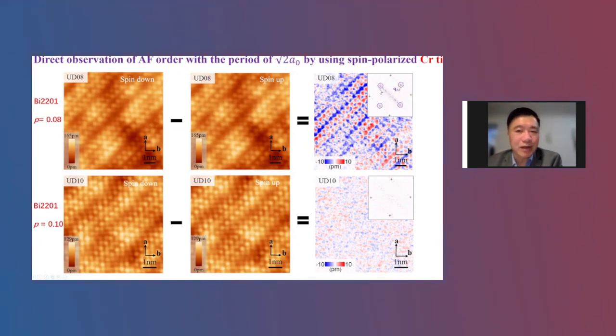So I must say that this is the very first time to directly visualize the anti-ferromagnetic order in the cuprate. Okay, and for the 10% doping, then you don't. We also measure spin down, spin up. Then we subtract. We don't see such order. After Fourier transform, we also don't see the spots. So that means that the anti-ferromagnetic order exists at the 8% doping sample, but on the 10% doping sample, it does not exist.